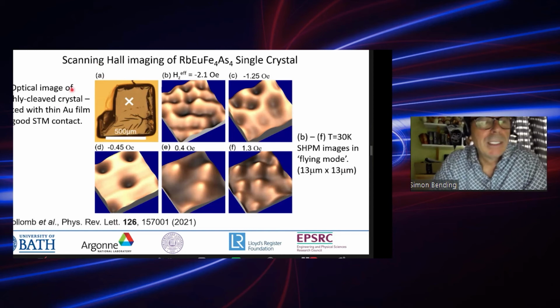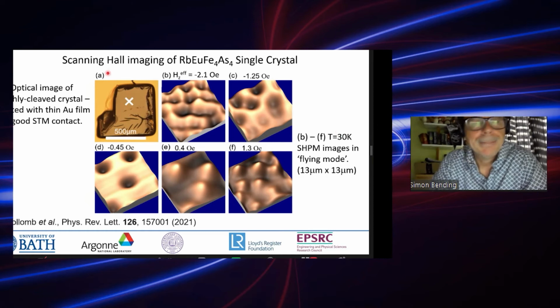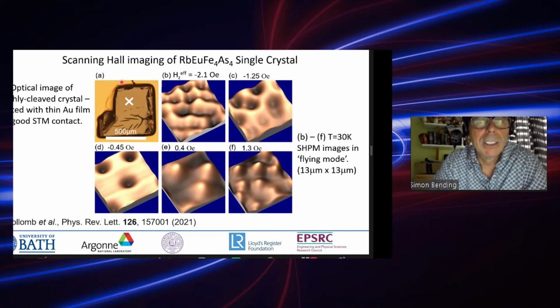So this shows then our first images of one of our crystals at 30 Kelvin. Before we mount the sample in our microscope, we freshly cleave it. This shows an example of a freshly cleaved crystal where we deposit a thin film of gold on top to make a very good contact with the STM tip on the Hall sensor itself. And you can see we've got this very nice atomically flat plateau here, and we take our data in a region roughly corresponding to the white cross that I've shown you here.